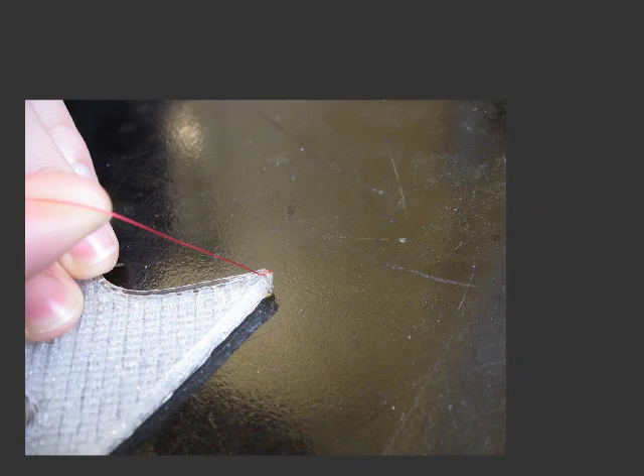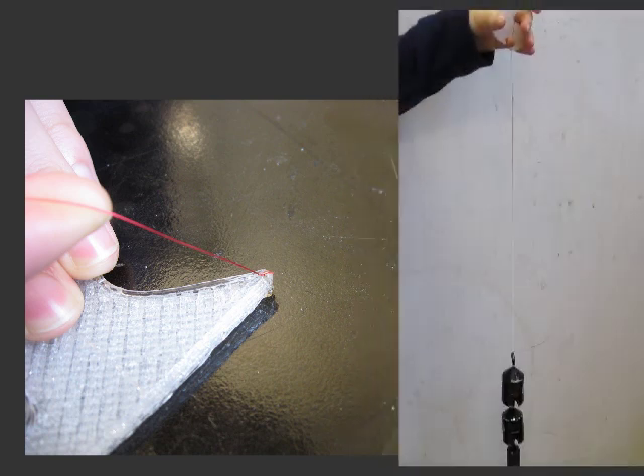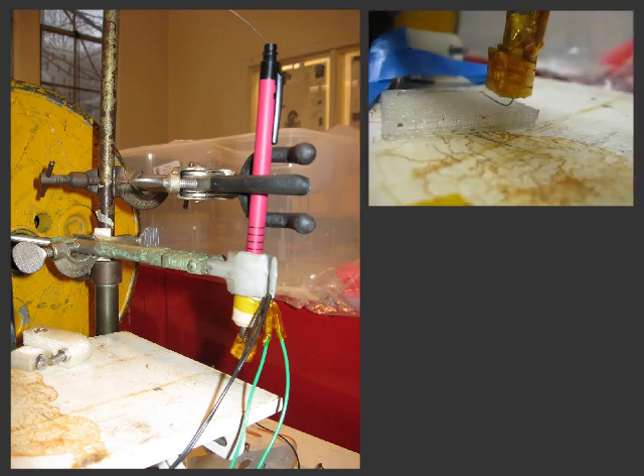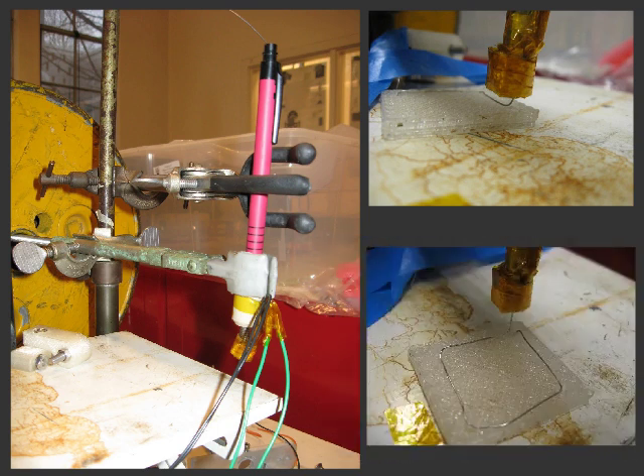Bonding wire to plastic is a crucial step in our process. We observed that the RepRap's thermoplastic forms a tenacious bond with metal wires when heated. This worked for copper and also steel wires, even enamel-coated magnet wire. Next, we built a mock-up of our device and operated it by hand on the benchtop. We were able to determine operating variables, such as what temperature the tip should reach in order to create the bond. We also tried different algorithms for printing wire patterns to see what pattern of heating, cooling, and motion worked best.